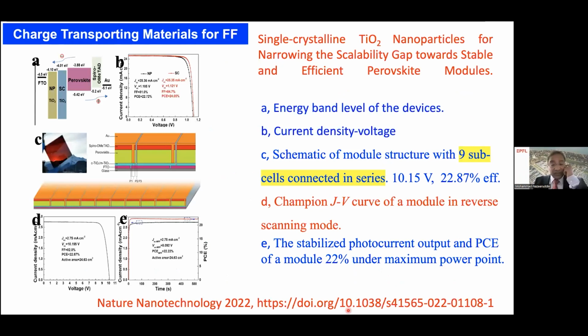Now I come to a very recent publication. Still we are modifying our ETL layer. In the previous study, what I mentioned was this type of ETL layer, that's nanoparticles, which has a LUMO level of the conduction band at -4.1.